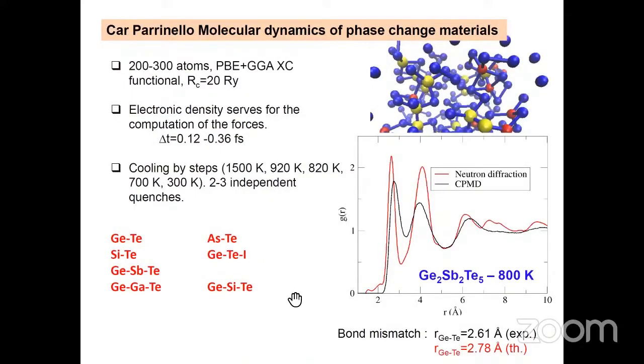So let us switch now to phase change materials. For phase change materials, we have been playing with systems with about 200, 300 atoms. Here are some details for those who have some interest. It's a PBE exchange correlation functional with a GGA approximation. The cutoff is about 20 Rydberg, and to integrate the equations of motion, we use a time step which is about 0.12, or 0.2, up to 0.36 femtoseconds.